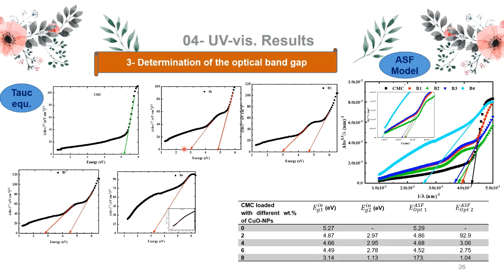The two models are in good agreement with each other, where they confirmed that all the nanocomposite samples have two transitions, which means that all the films contain two values of the optical band gap. The addition of different weight percentages of copper oxide to CMC reduces the indirect band gap of CMC, as we see in the table.